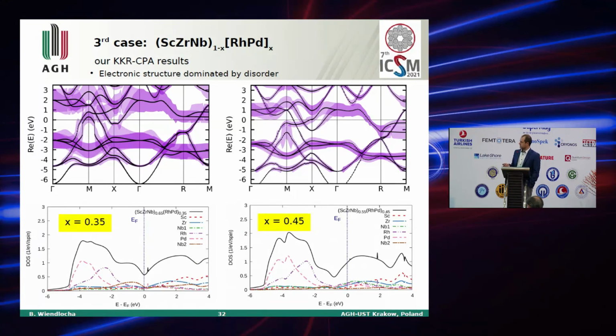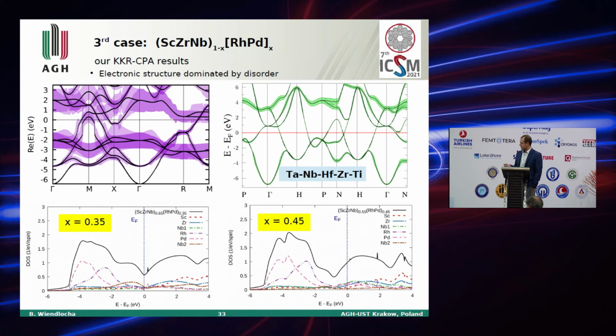And here is the electronic structure of the material. As you can see now, compared to the first material, the electronic structure is very strongly smeared by the disorder. So instead of having such sharp bands, this shading is an imaginary part of the energy which is calculated in KKR-CPA, so it describes the strength of scattering. So this electronic structure is strongly smeared because of disorder, which was not the case here. So the effect of this disorder here is much more important.